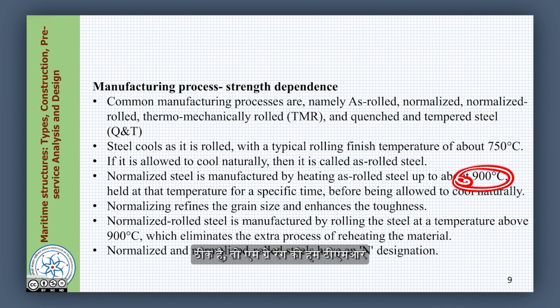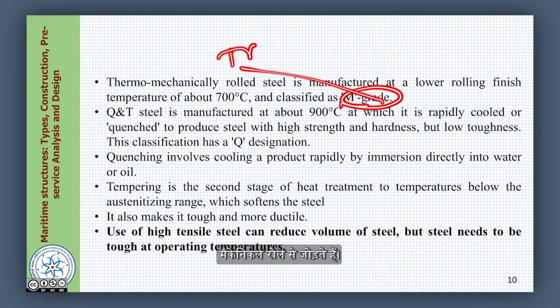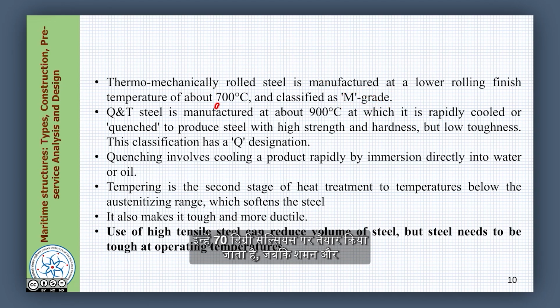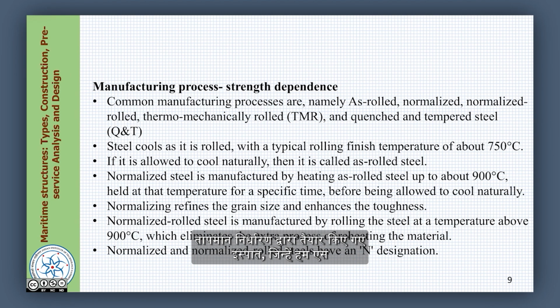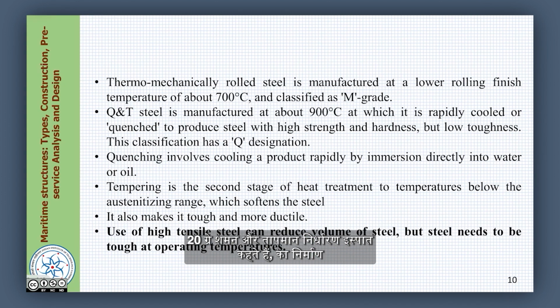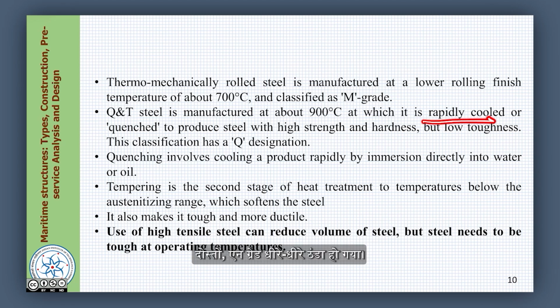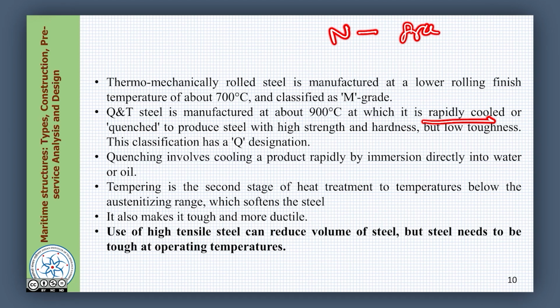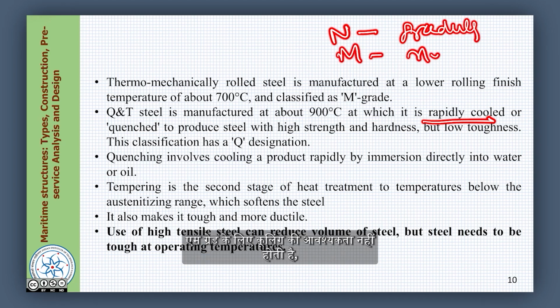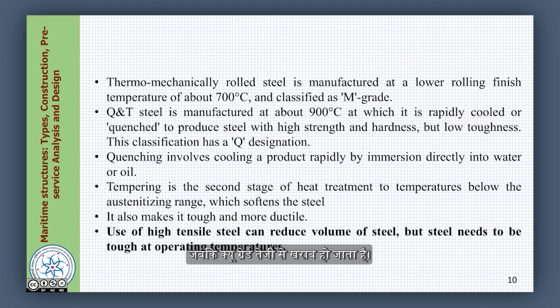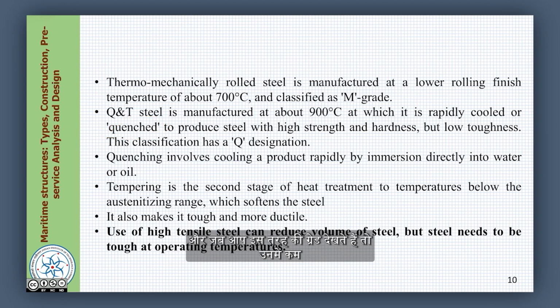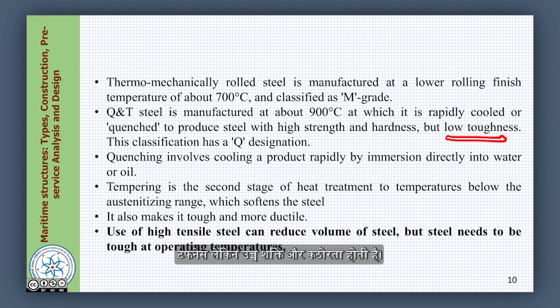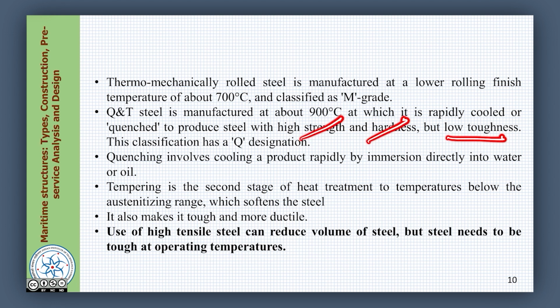Okay? So, M grade is what we associate with TMR, thermomechanically rolled. They are done at 700 degrees Celsius, whereas quenching and tempering steel, what we call Q&T grade, is manufactured at about 900 degrees Celsius, which is rapidly cooled. Friends, N grade cooled gradually, M grade no cooling necessary, whereas Q&T grade rapidly cooled. This is what we call quenched. Okay? And when you see this kind of grade, they have low toughness but high strength and hardness. They are classified as Q grade.